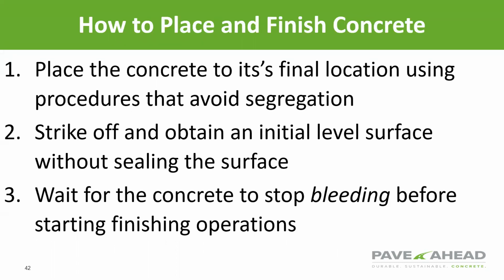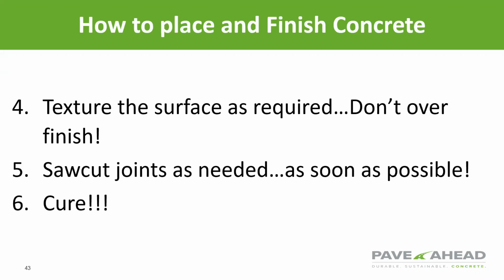So how do you want to place it? You want to place the concrete so that it's placed in its final procedures that avoid segregation. You want a level surface without sealing. Wait for the concrete to stop bleeding. You want to texture the surface as required. Just finish it so that you're able to get elevations that you want. You want to saw cut the joint. Try to do that as soon as possible.